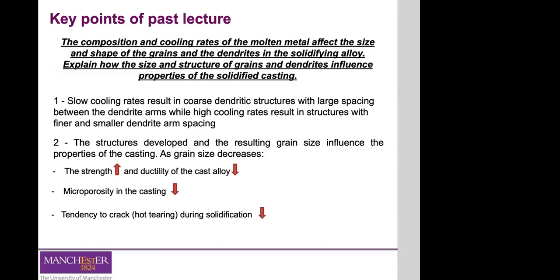Because we have finer grains, we have fewer voids between the particles, which results in a decrease in porosity of the casting — beneficial because what we want is a 100% solid structure. Also, by decreasing the size of the grains, the chances of having cracks or hot tearings during solidification from the molten state to the solid state will also decrease, minimizing the chances of hot tear defects.